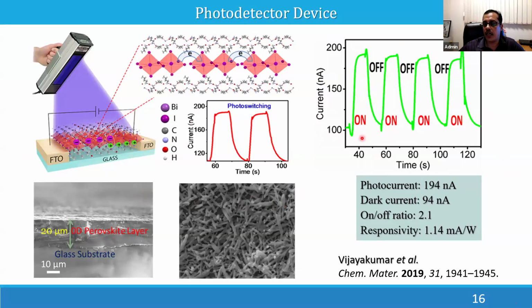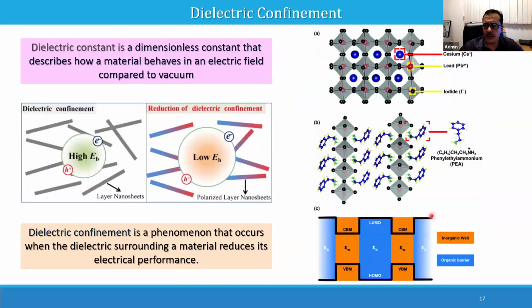So from 100 nanoampere, we were able to get something close to 200 nanoampere with an on-off ratio of 2.1 and a relatively good responsivity of 1.14. And at that time, it was good enough. Like in 2019, this 1.14 milliamps per watt responsivity and an on-off ratio of 2 is good enough. But of course, during the last several years, we improved the numbers to very, very high values, and developed some of the state-of-the-art perovskite photodetectors. So before going to that recent work, I will explain what we did after the second material.